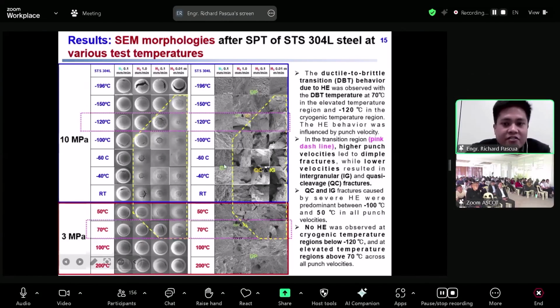Moreover, ductile to brittle transition behavior due to HE influenced by punch velocity was observed at negative 120 degrees Celsius at cryogenic temperature and 70 degrees Celsius at elevated temperature, from intergranular fracture or brittle fracture to dimple fracture or ductile fracture, in which the highest punch velocity showed the predominant dimple fracture and the lowest punch velocity showed an intergranular fracture. Moreover, small ring-shaped cracks and a combination of quasi-cleavage and intergranular fracture was observed between negative 100 to room temperature, showing the severe hydrogen embrittlement effect at these temperature conditions at all punch velocity.